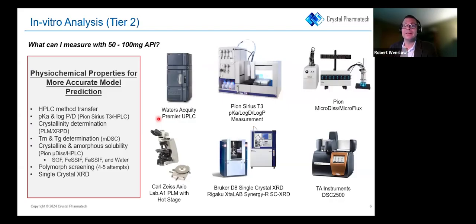And with that, you, number one, have absolute, well, depending on how heavy an atom you have in there, you can get absolute structure determination, absolute stereochemistry, definitely absolute structure determination. But then also you can use that in the polymorph prediction to then really quickly get an idea of where you're at in the polymorph landscape. It really cuts down on the cost and the speed of the polymorph prediction.